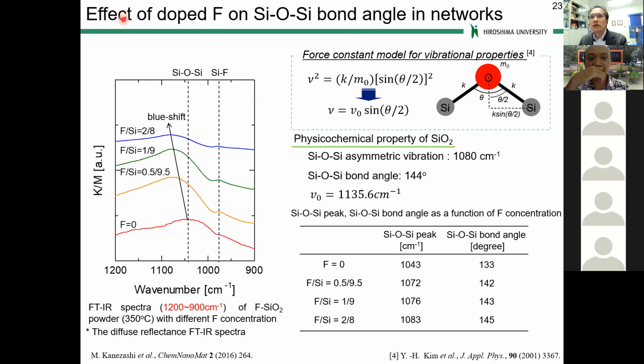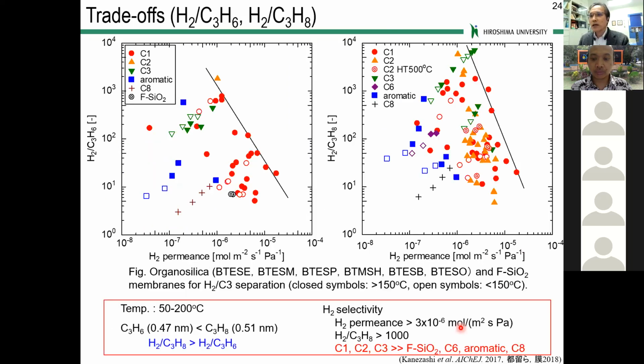This was further examined by measuring FTIR. We can see that by doping fluorine at 0, 0.5, 1, and 2, there is some blue shift of the siloxane bonding, and this indicates that the Si-O bonding is becoming large in bond angle, making a looser structure. This also summarizes the trade-off of hydrogen over propane and propylene.